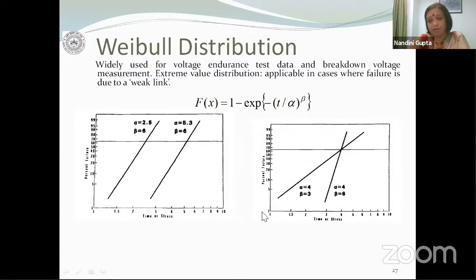If, on the other hand, you look at the data on the right-hand side, again, I have two materials and they both have the same value of alpha. So 63.2% probability. The other probability values are different, but the 63.2% probability value for both materials is the same, and that is equal to alpha equal to 4. So therefore, the breakdown strength or the time to failure that I expect to happen with 63.2% probability is the same for both materials. So one would imagine that there is no reason to choose either one of them, but there is, because if you look at their beta values, the beta values are different.